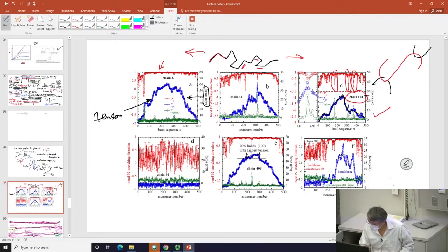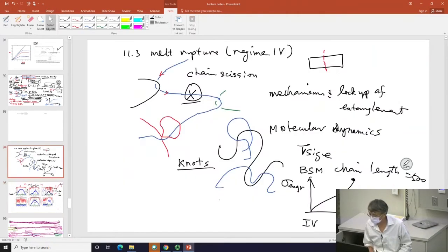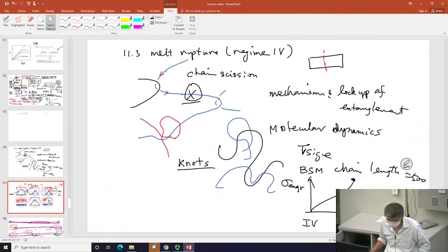And if you read the level of stress, it turns out this is reaching a level of 0.1 nanonewton. That's a huge, huge number. Remember, it takes only 3 nanonewton to break the chain. So this is, let me see, it's more than that, in fact. This is close to 0.5 nanonewton, actually. So it's quite large, a very, very large amount of stress.